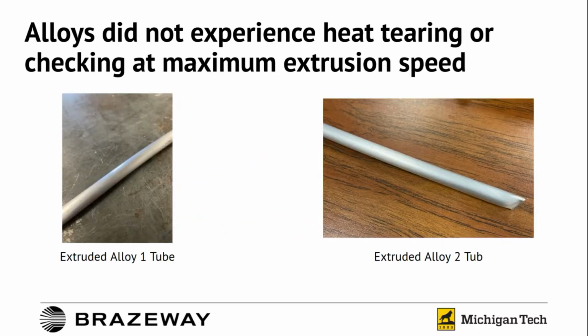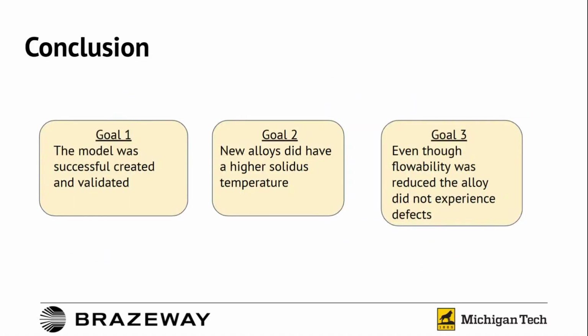Even with that decreased flowability, though, we did run the extrusion press at its maximum speed of 30 inches per minute. We did not see any significant hot checking or heat tearing. So in conclusion, our model was successfully created and validated for Brazeway. Our alloys did in fact have a higher solidus temperature, so goals 1 and 2 are completed. Goal 3, even though these alloys had reduced flowability, the alloy did not experience any significant defects.